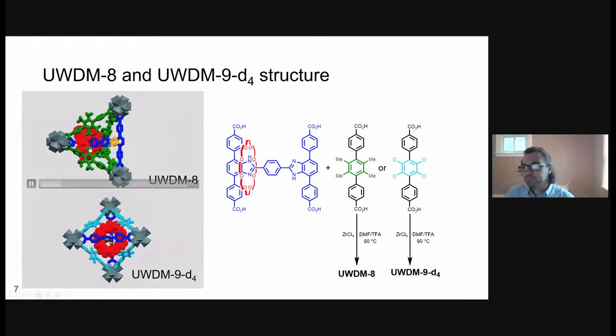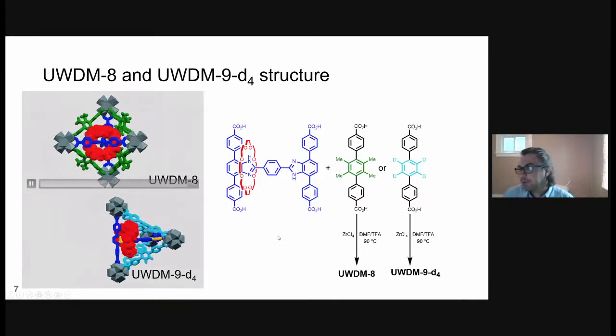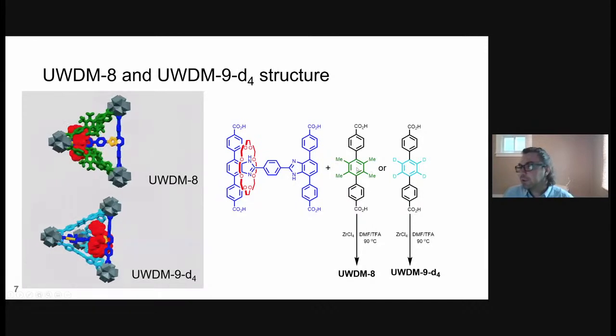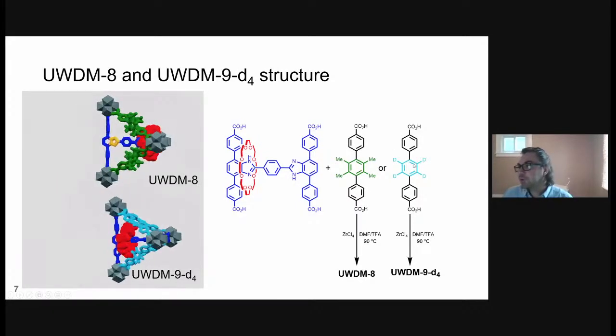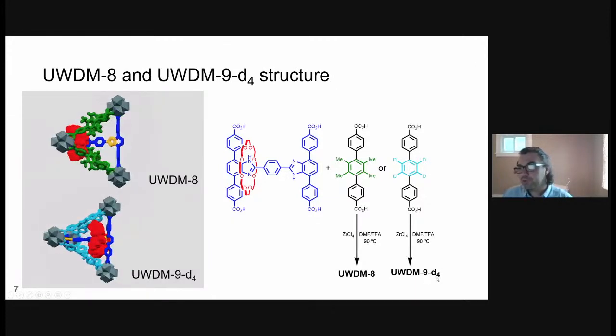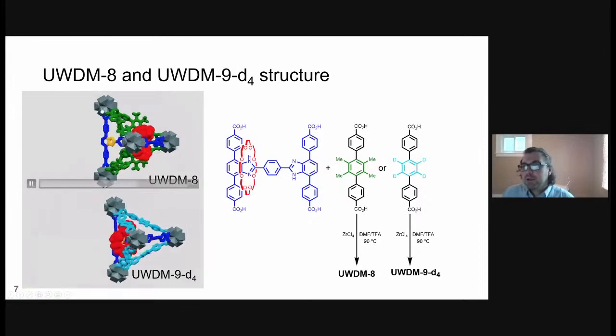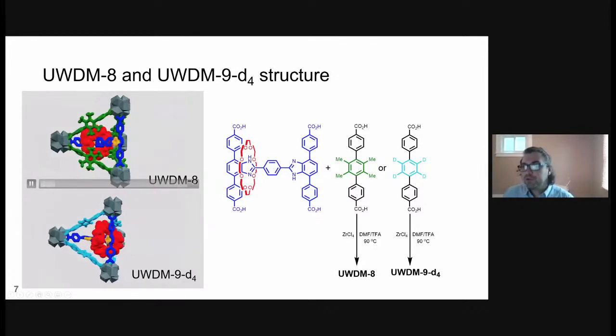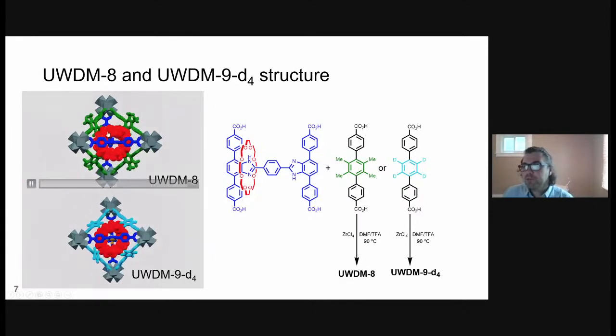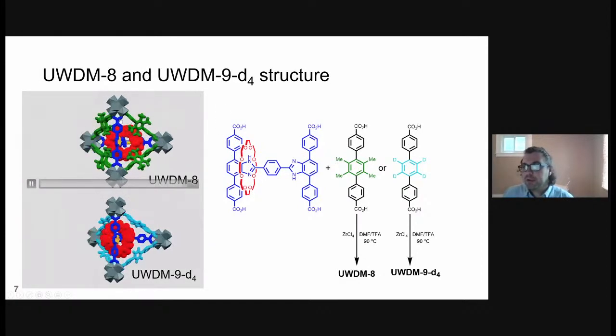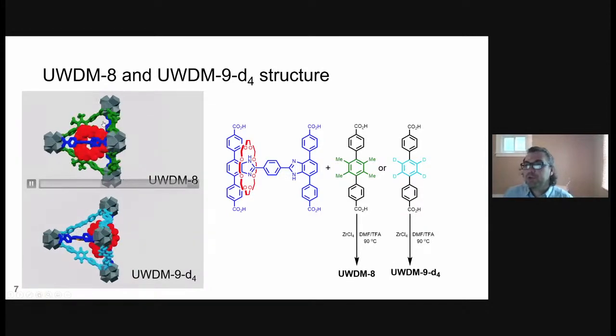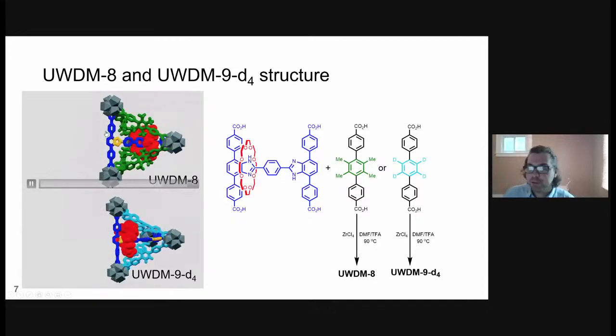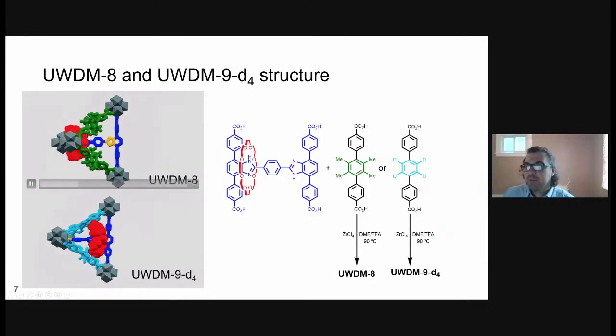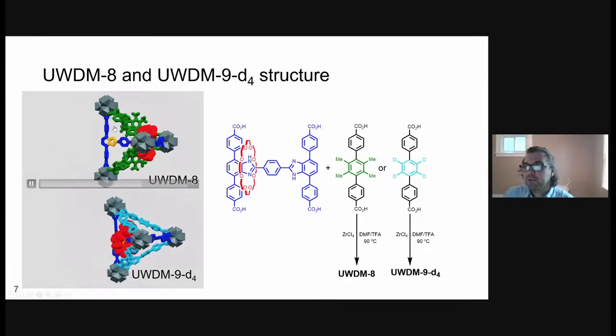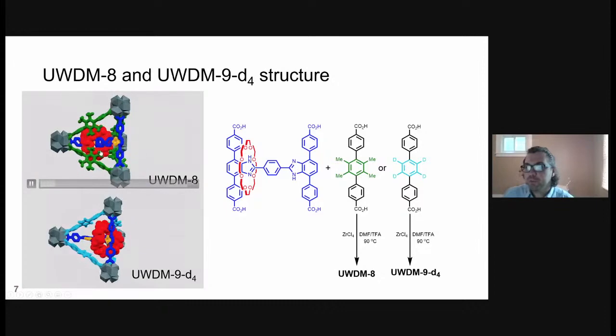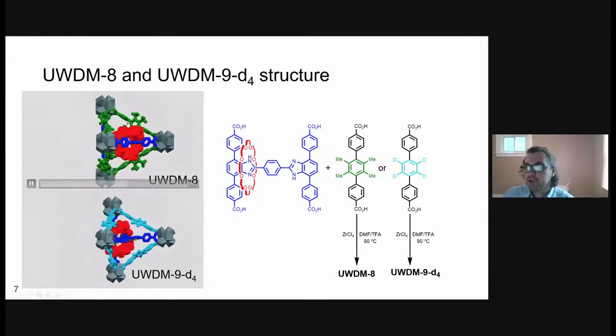So in terms of what these cross-linked tetrahedral cavities actually look like, when we take this ligand and either the tetramethyl coligand to give UWDM8, or this deuterated phenyl coligand to give UWDM9-D4, because of these deuteriums. And we built these models in Materials Studio just to get an idea of what these tetrahedral cavities will actually look like. So in the case of UWDM8, we can see these tetramethyl coligands, these central spaces are perpendicular to the linker plane with these methyl groups orientated directly into the tetrahedral cavity. And they're locked in that position due to the steric bulk of the methyl groups, and they're potentially going to impede any translational motion of this macrocycle from this recognition site that is currently in orange to the other one.